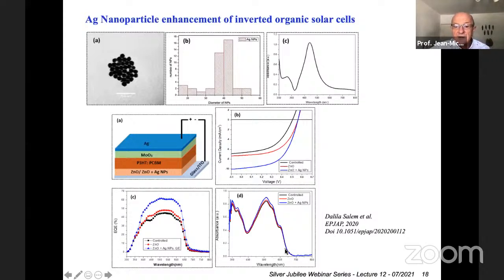And with the presence of the nanoparticles, we see an increase of the absorption, which is very much reflected by the external quantum efficiency of a solar cell, in which the blue curve with the nanoparticle is mostly uniformly increased vertically, not laterally, not a variation of absorption. So it shows that it is mostly a scattering effect more than a specific absorption due to the plasmonic resonance. And it increases the photovoltaic efficiency.